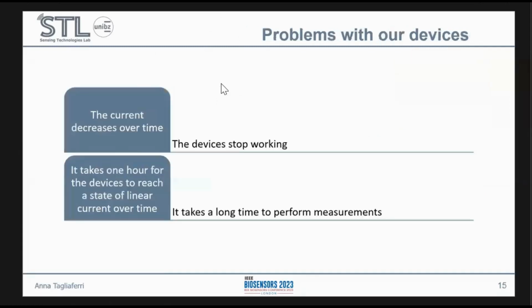Just recapping a little bit the problems that we obtained with these three devices. In the first two cases, we had the carbon nanotubes not protected by any kind of membrane, and what we experienced is that the current decreases rapidly over time. This leads to devices to stop working, which is less than ideal. Moreover, they are single-use, and we have to throw them away very quickly.